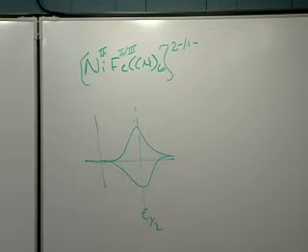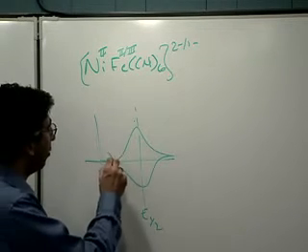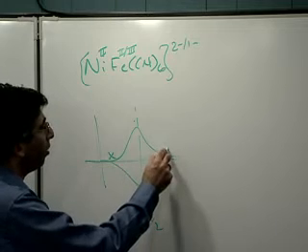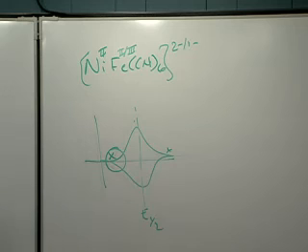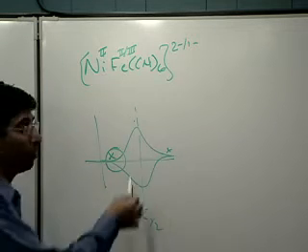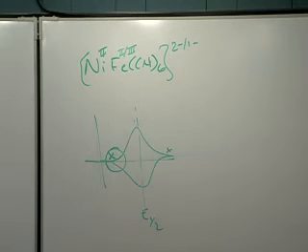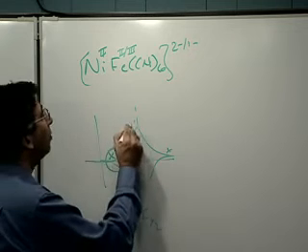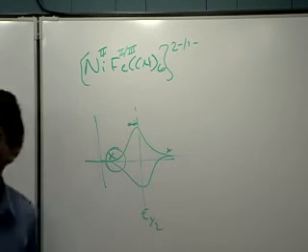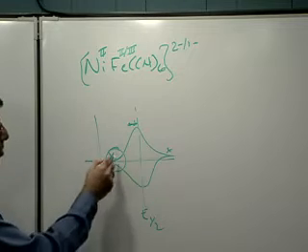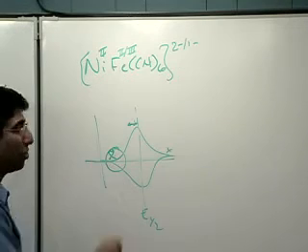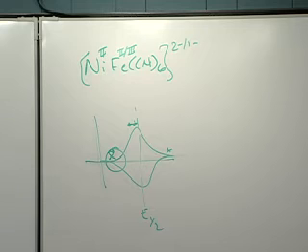And we're going to want to run our CVs, our AC experiment, either over here or way over here. And we picked over there because we were concerned about corrosion out there. Why? Because if we do it somewhere around here, then we're getting massive changes in the number of ions as we change the potential there. Even if we made a small potential change here, we're making a big change in the ratio of oxidized to reduced. Whereas if we do it over here, then the change is pretty small. And so we'd expect we're not making much of a structural change.